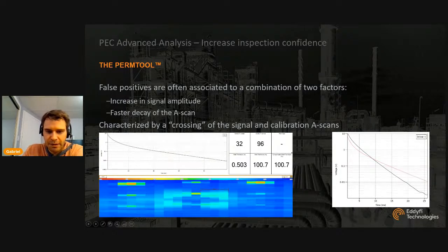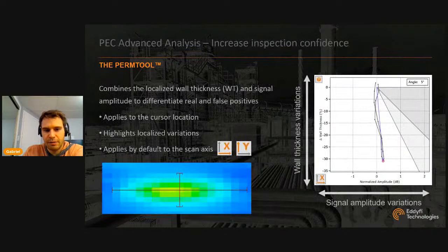So in most cases, that's going to be characterized by this crossing of the A-scan. It's an extreme example, but you see higher signal amplitude at the beginning of the A-scan and then a faster decay. So we built a tool that's going to combine those two pieces of information in one, signal amplitude as well as the wall thickness variations.